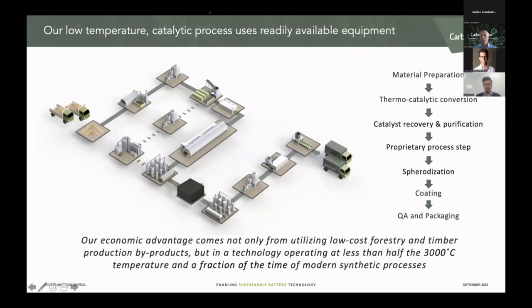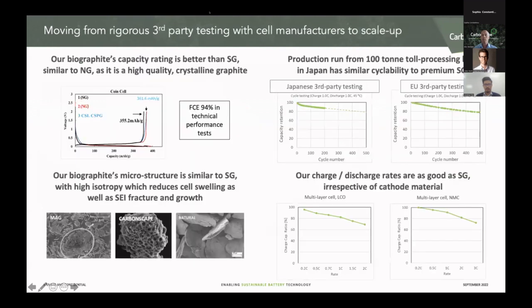And it delivers a very high performance biographite, which is coated and spheroidized like other synthetic graphites. In terms of performance, we've done a lot of testing with third-party testing, but also with our cell partners, who are industry partners, both anode manufacturers and cell manufacturers. And we have a first cycle efficiency of around 94%. The microstructure is very similar to synthetic graphite, and therefore there's not very much swelling in the end cell.